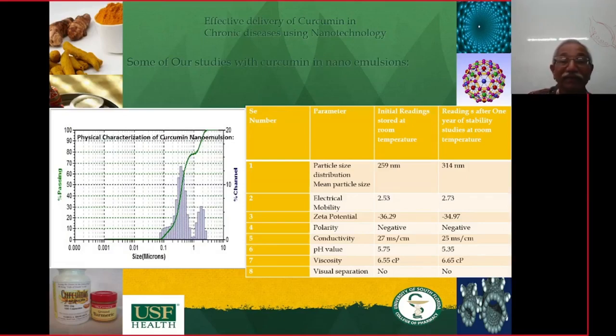You'll find that our particle size of the nanoemulsion was 259 nanometer, and even after one year of stability study, the particle size did not change much. It came only 314. The electrical mobility was 2.53 to 2.73. So this was a very stable nanoemulsion we had created. Their pH value did not change much, their viscosity did not change. Their zeta potential was very high. Higher the zeta potential, better is the stability.